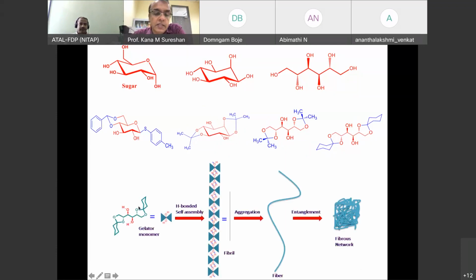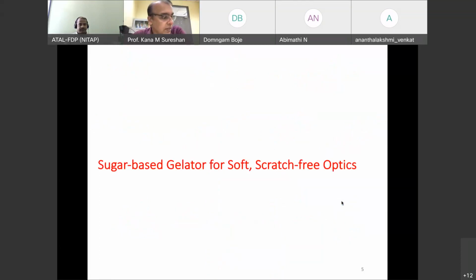That network is only a schematic. Actually, the dumbbell you see with the two OHs is the schematic of the molecule on the left side. Now the dumbbells having OH will hydrogen bond to form a chain, a hydrogen bonded chain, and such a chain you can call a fibril. Several such fibrils laterally aggregate and form much thicker fibers, and such fibers entangle in 3 dimensions and make a fibrous network like a spaghetti or noodle-like network. There are a lot of spaces in between, and in the spaces the solvent goes and gets trapped. That is what a gel is. So the gel has both a solid and a liquid component.